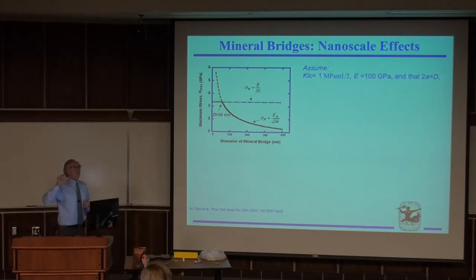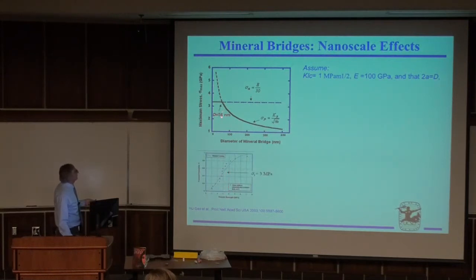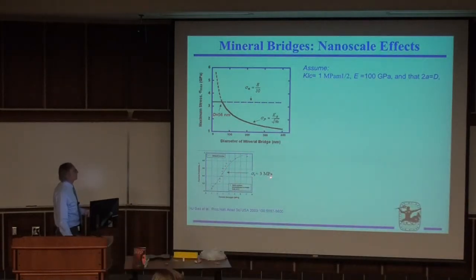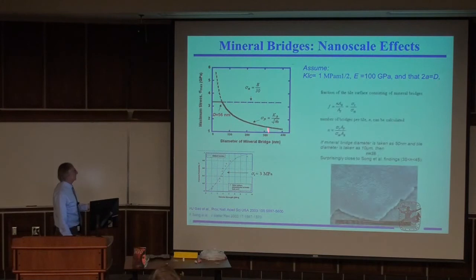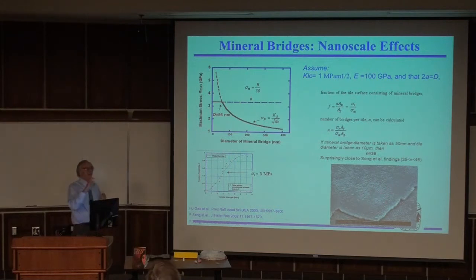This is approximately the dimension of this little bridge. These bridges are about 50 nanometers thick. So nature has reduced the little bridges to the size where they cannot get any stronger. Now if we go to calculations, we know the strength of each bridge would be about 3 gigapascals, and we multiply the strength by the area here. We can then calculate how many bridges we would need to get 3 megapascals. We go through it, and we get 36 bridges. And Song found that it's between 35 and 45 bridges. So if you look at all these bumps here, only 1 in 10 or 1 in 20 will be a bridge. The other ones are just bumps.